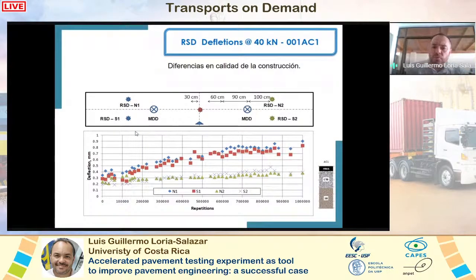Well, here you can see the variation between two different points of a single test track. Basically the green dots or triangles and the yellow and the red ones were measured in two different places of the same test track. And you can see why you can explain this difference. It's basically construction differences. So talking to guys like the South Africans, Wynand Steyn, Louw du Plessis, Maurice de Beer, or talking to John Harvey, to Dave Jones from UC Davis, to Gusset Chuain from the Florida Department of Transportation, they recommended that we perform different analyses on both sides of this test track. It's basically because we are assessing a normal thing: due to different construction conditions, you can have different behaviors in your pavement, and all of you know that.